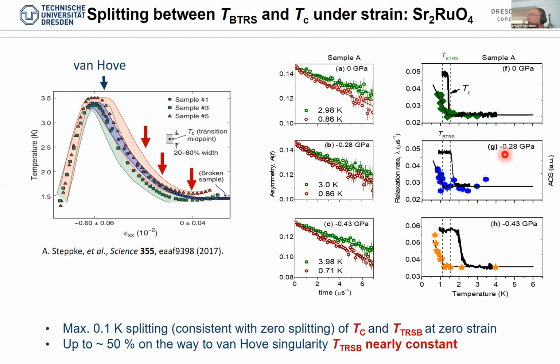But then if we go to a little bit higher strain already, you see that as was known already, the TC increases, but as you can see here, the temperature where time reversal symmetry breaking exists is more or less constant. So there is a splitting developing, clearly, even if we go to a little bit higher strain, you see it here, but what is kind of astonishing is that more or less there is no change of the temperature at which time reversal symmetry breaking appears. So the temperature T_TRSB is nearly constant.